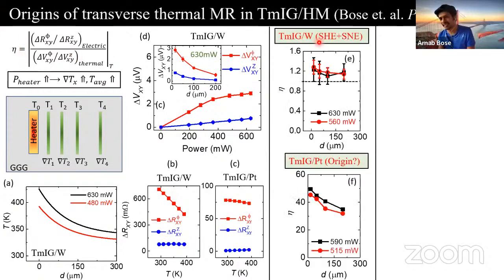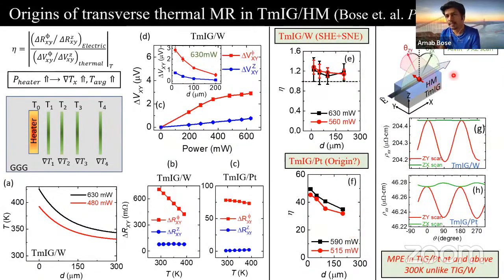So for TMIG tungsten, we find that the value of eta is very close to 1, suggesting the origin is spin Hall and spin-Nernst. But for TMIG platinum, this value is substantially different from 1, meaning there must be some extra contribution, and we need to know what it is. So for that, we measured the traditional electrical SMR by measuring the longitudinal sample resistance while rotating the magnetic field out of the plane in XZ and YZ. The XZ scan will give us an AMR contribution, which is a property of a conducting magnet, and the YZ scan will give us the information about SMR, meaning we'll pick up the information for spin Hall effects.